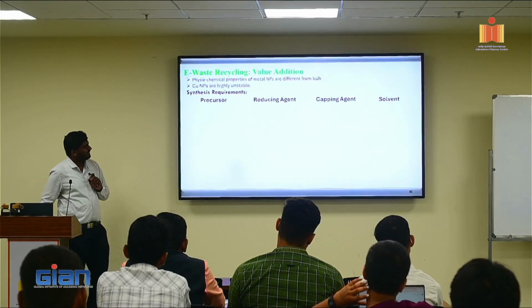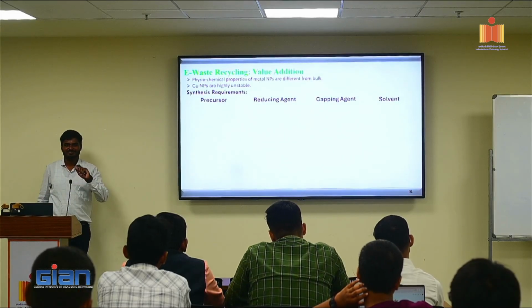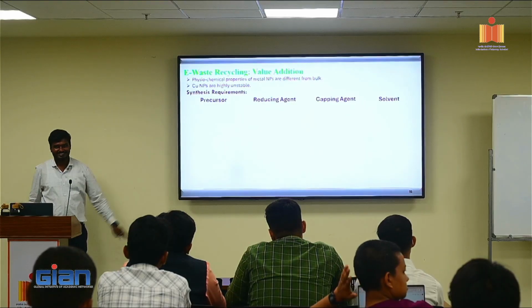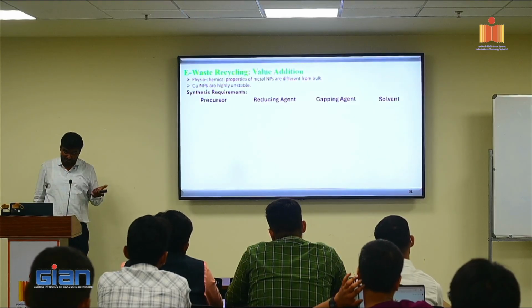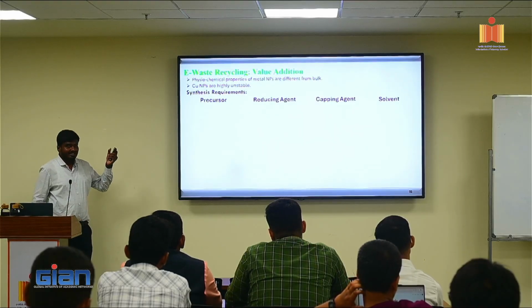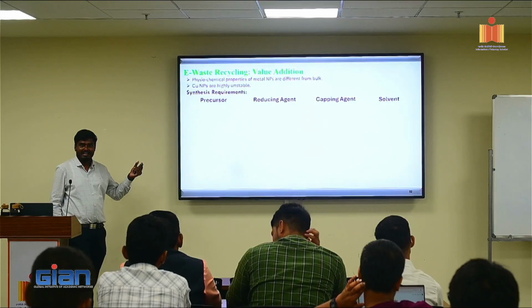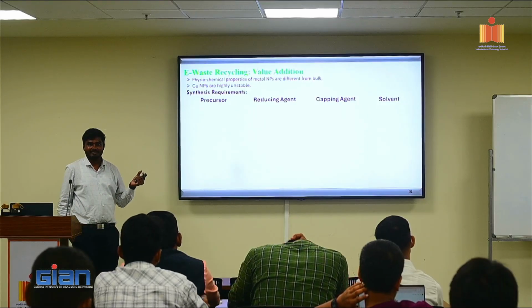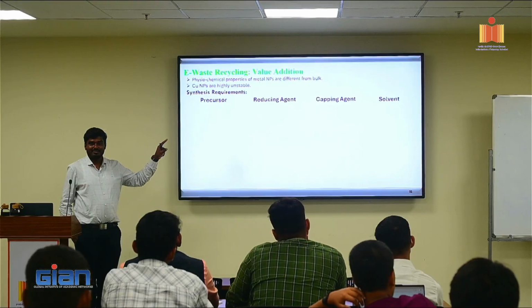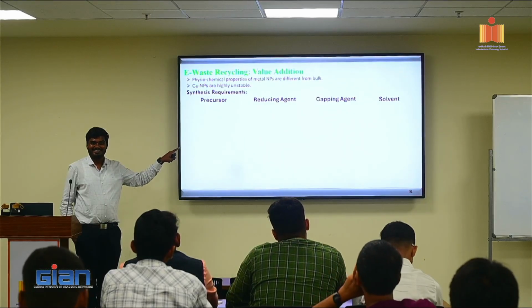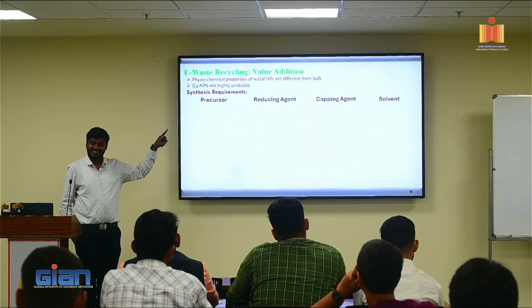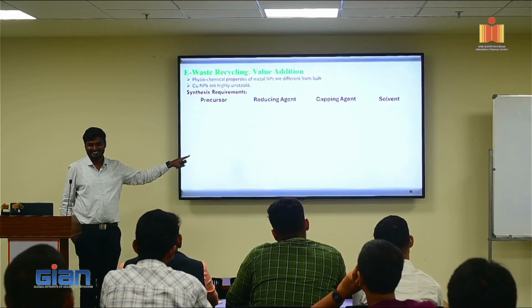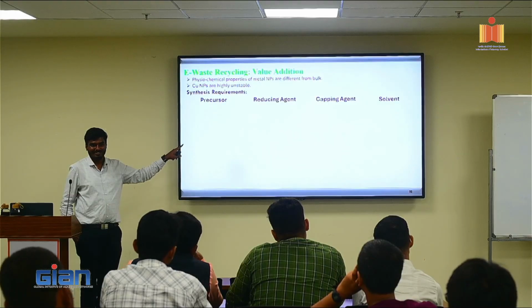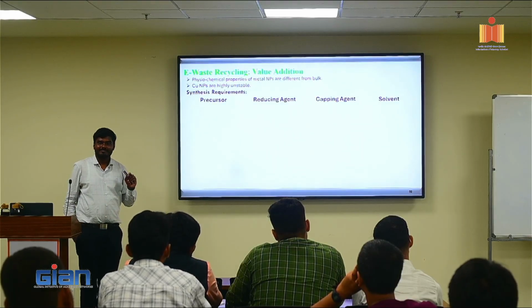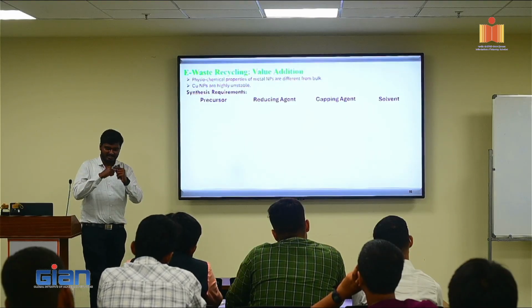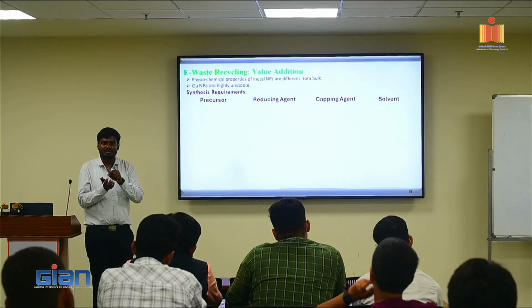Then we thought, what are all the recipes that are necessary for copper nanoparticle synthesis? One is the precursor. Precursor means the raw material. That is my copper nitrate solution. So I have a Cu2+ solution and I have to convert it to Cu0. So we need some reducing agent to convert that. Here I don't have any option other than using a reducing agent, so I have to definitely use another chemical for this process. That's why we still didn't focus on scale-up, but we are doing this. Then the capping agent. Basically what a capping agent does is it will try to form a thin layer around the particle and it won't allow it to grow.